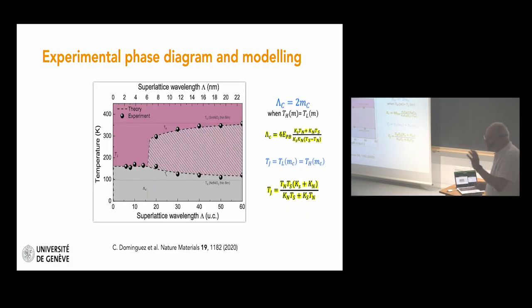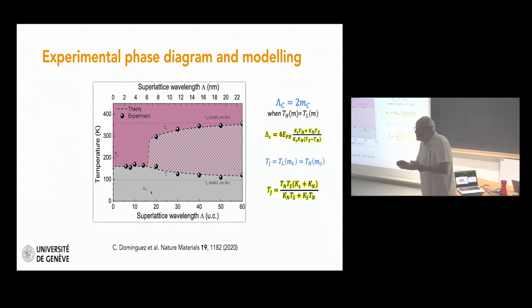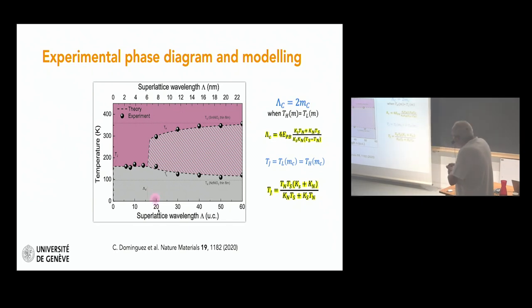Okay. We've been trying to go in this direction, because what we do here is, in some sense, kind of obvious. If you know the critical wavelength, for a given energy there will be a critical wavelength, because the denser the interface density, if you have too many interfaces, you will not allow for this mixed state. So here we use lambda c as a fitting parameter, so we are not really calculating this.